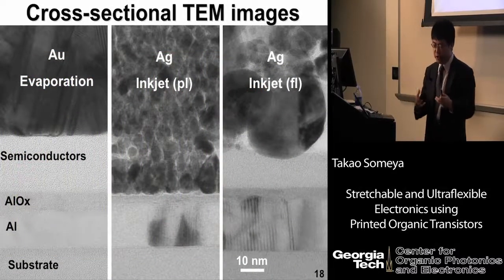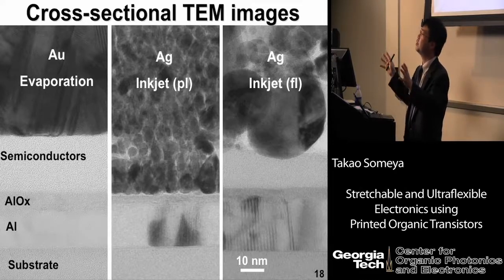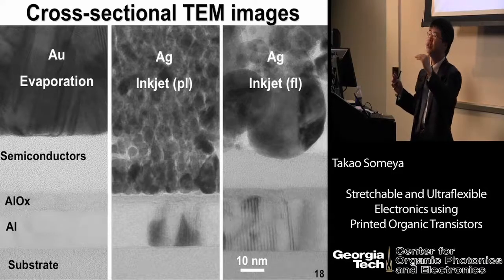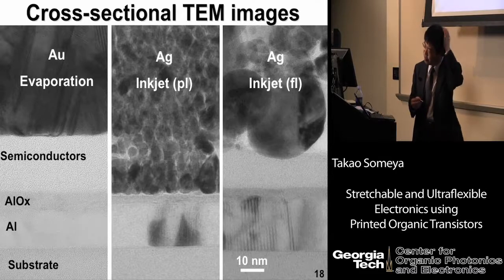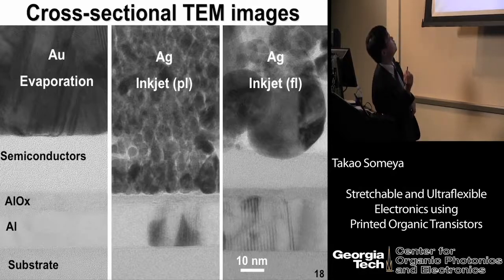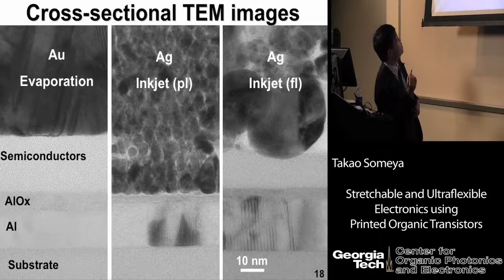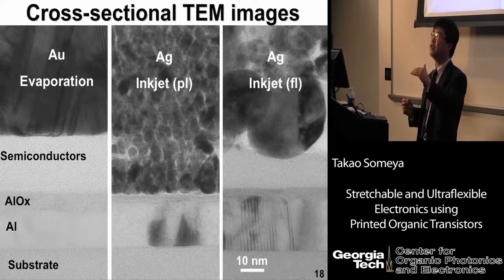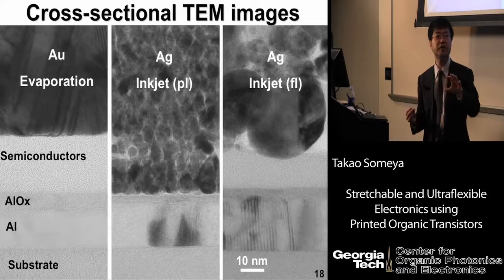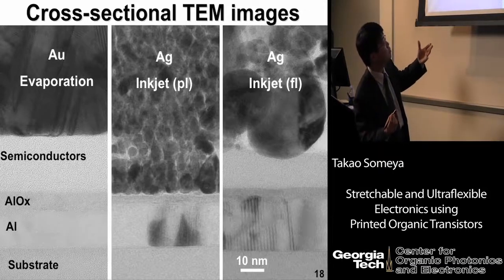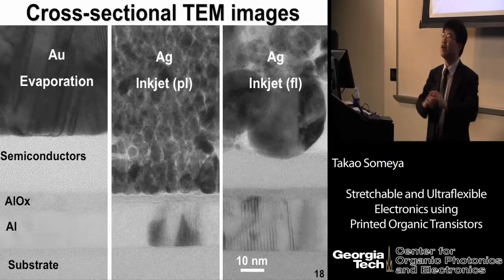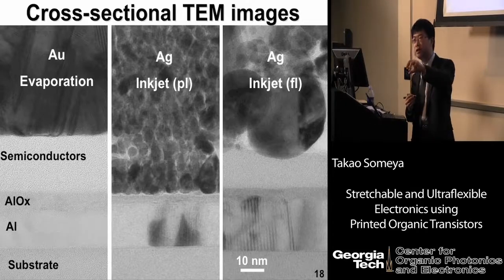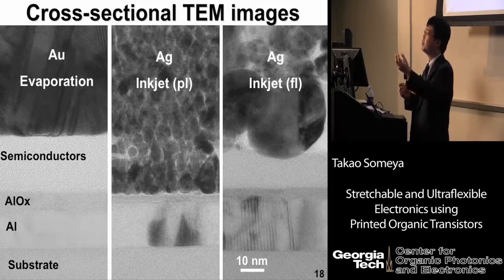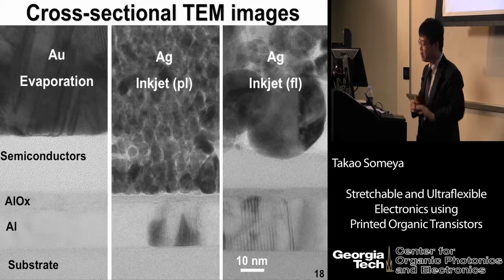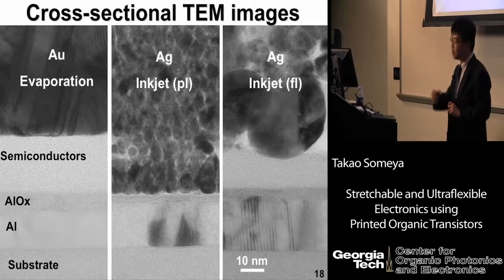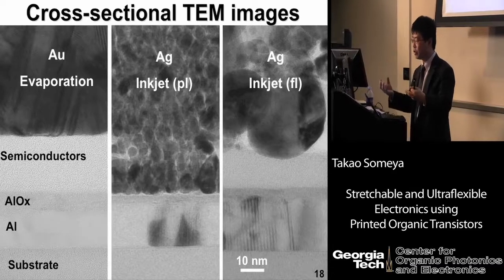In order to improve the device performance, of course, this is the active component, so careful control of interfacial quality is extraordinarily important. This is one of the good examples. If I deposit the gold by evaporation on the surface of semiconductors, here you can see the abrupt interfaces can be nicely formed. However, if I use the picoliter inkjet, here is a problem. Organic solvent is penetrating into the semiconductor region, so now you cannot see any interface. However, if I use the sub-femtoliter inkjet, all the organic solvent is vaporized before it reaches the substrate, and then we can avoid the organic solvent associated degradation. In this way, we can fairly nicely control the interfacial quality.